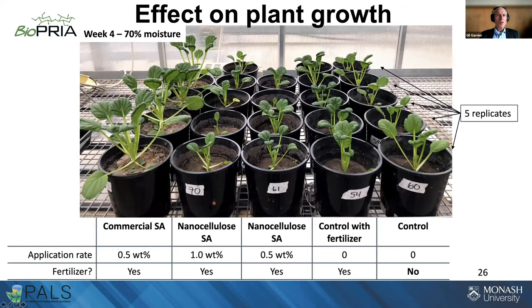We grew spinach to test the gels. Seeds were planted, grown to six weeks with five replicates at 30%, 50%, and 70% moisture content. The largest plants came from the commercial petrochemical superabsorbent. The high-dose nanocellulose (1%) actually performed worst. This was puzzling because the water absorption ability of nanocellulose is as good as the commercial superabsorbent, yet the natural, biodegradable nanocellulose did not perform as well in plant growth.